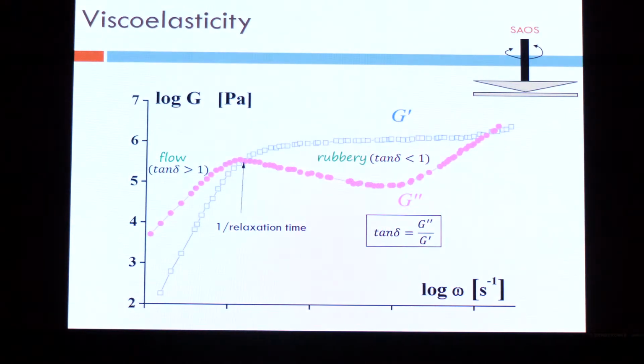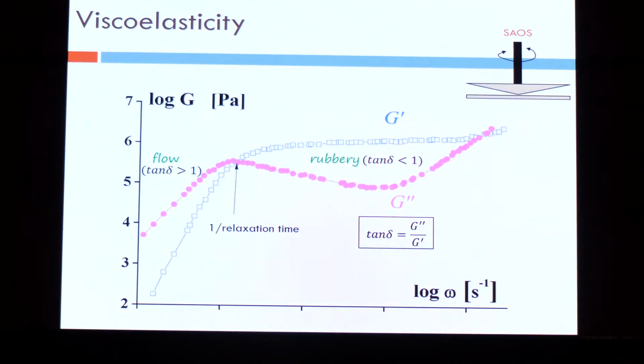Okay, and therefore now if you do this experiment of measuring the viscoelastic properties of this liquid, you're measuring two things, something called the G prime and the G double prime. The G prime measures the elastic part, the solid-like elastic part. The G double prime measures the liquid-like viscous part. You will see this interesting graph where on the x-axis is the frequency. That is, I am measuring how fast I am doing these motions. I can do them very slow or I can do them very fast. Depending on how slow or fast I do, and I measure the G prime and the G double prime, the elastic and the viscous part, I get a graph that looks like this.